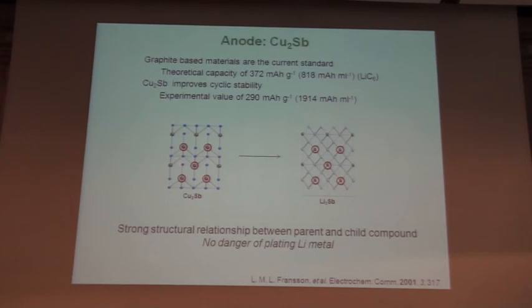Then it charges to form this compound, lithium antimonide, and notice that the antimony atoms don't change structure. So they provide a framework that breathes in and out as copper is extruded and lithium intercalates, and it is very reversible. In terms of gravimetric capacity, it's heavier than graphite, so the gravimetric capacity is not as good, but volumetric capacity is over twice as high.